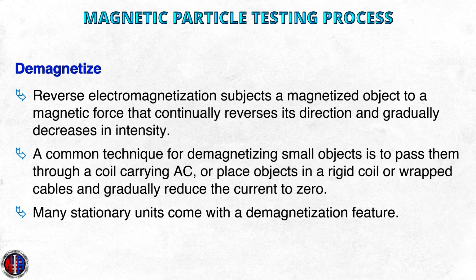Demagnetization can be accomplished using a variety of techniques. Reverse electromagnetization subjects a magnetized object to a magnetic force that continually reverses its direction and gradually decreases in intensity. This technique shifts the domains back to the random orientation. A common technique for demagnetizing small objects is to pass them through a coil carrying AC, or place the object in a rigid coil or wrapped cables and gradually reduce the current to zero.